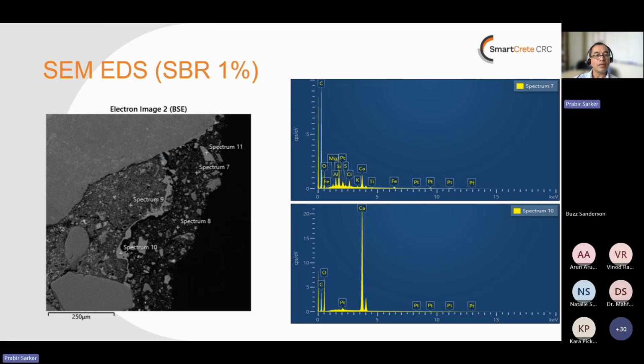Further looking at why it can improve, we have done some scanning electron microscopy and some EDS to find what is found in the pores. SBR latex has the carbon content. In some of the points, it was found that the carbon content was high, which shows that the SBR latex actually penetrated into the adhered mortar, and that carbon can be found inside the mortar.